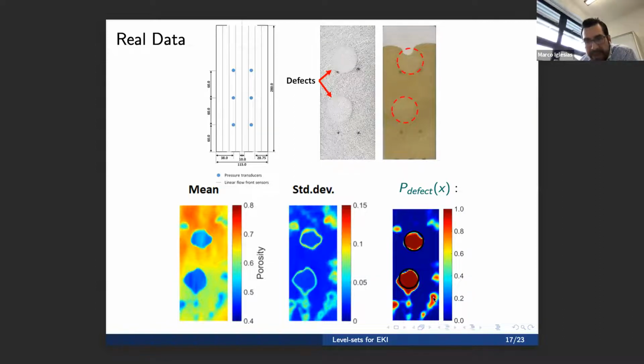Now, there are some areas that will need further investigation where they were not supposed to have this low porosity, but nonetheless, we capture that. And we know that this cannot be perfectly controlled, but we feel that this is a very successful example that with real data, we were able to capture these effects and characterize the values of these with uncertainty.